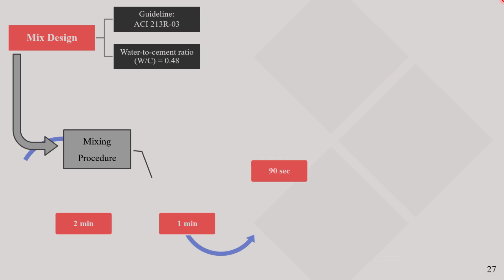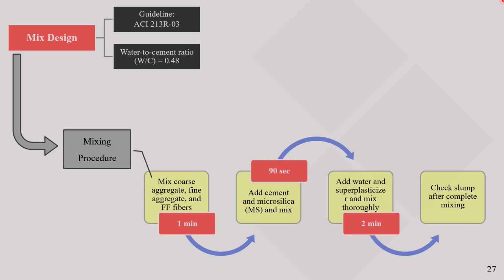Mixing procedure. The mixing was done as follows. First, coarse aggregate, sand, and Forta-Ferro fibers were mixed for 1 minute. Then, cement and microsilica were added. Finally, water and superplasticizer were added. After mixing, the samples were prepared for the slump test. After hardening, the other tests were conducted.